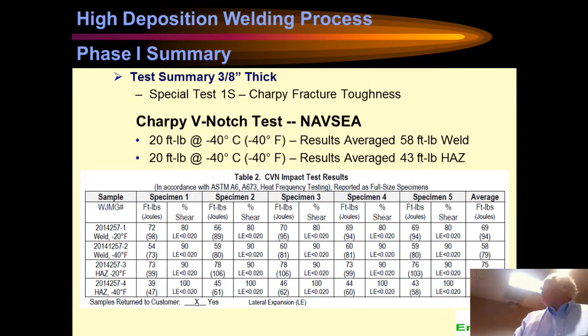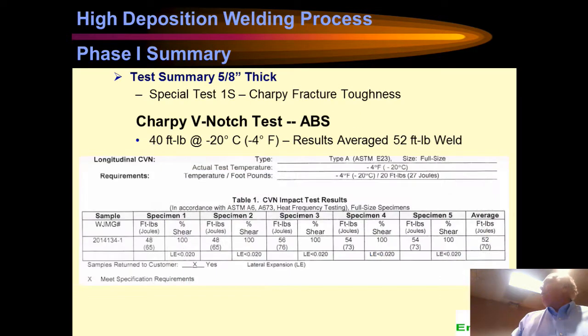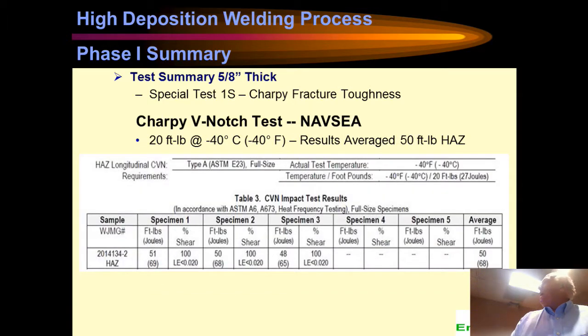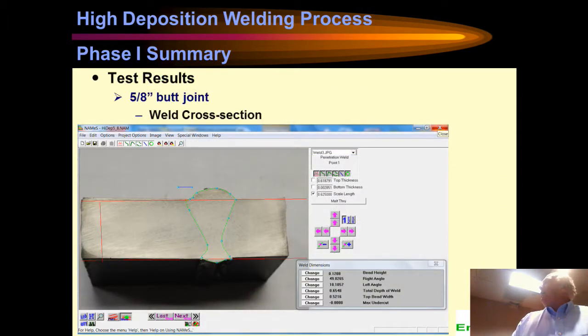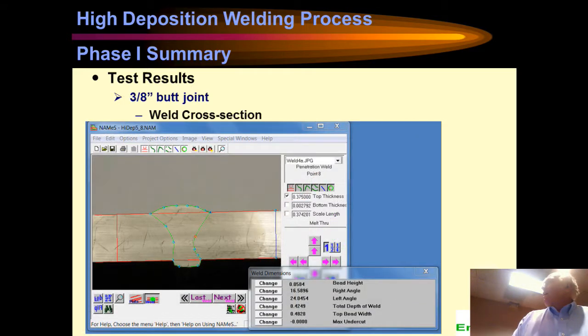The Naval Sea Systems ones require very low temperature Charpy, so we have to go down to minus 40 degrees with these, and in every case we more than met all of the requirements. This should look familiar to you, Jesse, because he did a lot of these tests for us. So both on the 5/8 and the 3/8, we met both the NAVSEA and the ABS or AWS. That's what our weld shape looked like. Almost parallel sides, top to bottom on the 5/8, and similarly on the 3/8 material.